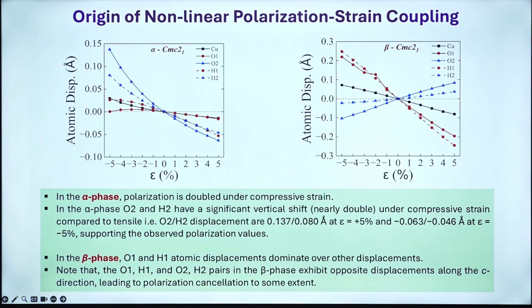This is the answer to your question. When you apply strain to the system, each atom will respond to that, and the interatomic distance will vary between the atoms on their own. So now we look at the atomic displacement and strain. In the alpha phase, the polarization is doubled under compressive strain. In the alpha phase, the oxygen and hydrogen have a significant vertical shift, nearly double under compressive strain compared to tensile. Okay, and O2/H2 displacement of 0.137/0.080 Å at +5% and -0.063/-0.046 Å at -5% supports the observed polarization values.